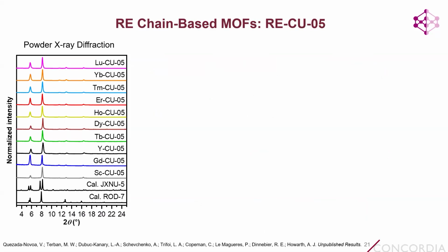So first we have the powder X-ray diffraction patterns for this MOF that we were calling CU-05. And we started by just trying to compare them to some powder patterns for other MOFs in the literature that had pyrene-based linkers. And so we found this JXNU5 as well as ROD7. And you can see that the powder patterns have a reasonable match, but not really overall that convincing. This particular MOF also does not have a lot of Bragg reflections, which made it particularly difficult to try to determine a structure from the powder X-ray diffraction patterns.